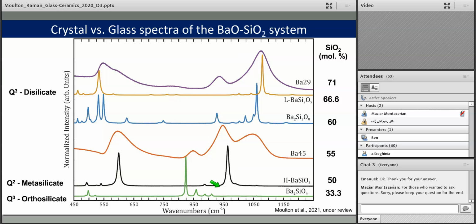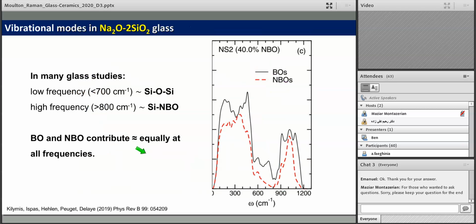And this persists, for example, these Q2 peaks appear in the glasses even as low as 30% or 40% barium, 45 or even 50. So there's a whole trend going from Q3s to Q2s. Maybe there should be a Q1 in here somewhere to Q0 between the glasses and crystals. And this is also true of these lower frequency modes as well, except that they're quite a bit broader than the crystalline vibrations here. And you see that for some reason, this high silica barium silicate glass here with 29% barium has sort of a doublet feature, but once you get to 45, it seems to have got rid of the peak that was here. So there are some very close similarities, and it seems that the glasses are following the general trends in the silicate crystals, but there are some significantly broader features and some subtleties between them.